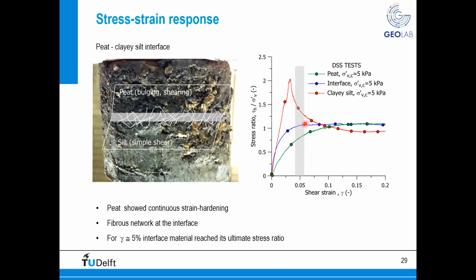So having an insight from the laboratory point of view into the different kinematic compatibility between the different layers is extremely important. And this kinematic compatibility, in our opinion, comes from the role of the fibers. The lateral displacement that you saw inside the peat layer was basically transferred to the clayey silt through this kinematic constraint of the fibers. And the clayey silt layer reached failure much earlier than the peat due to a completely different stress-strain response.